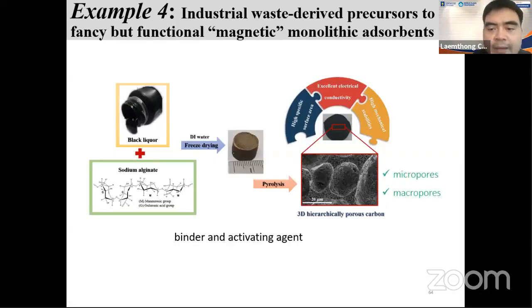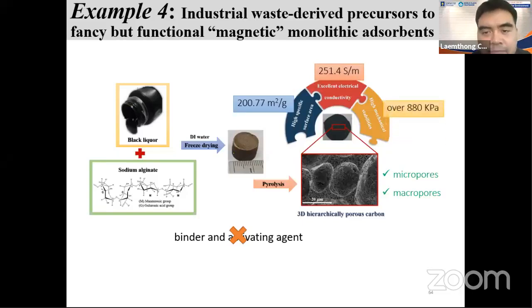So we use the black liquor to make the hierarchical carbon magnetic porous material, okay? And we can obtain around 200 square meters per gram, which seems to be okay as well. And it can be conductive as well. It is conductive.